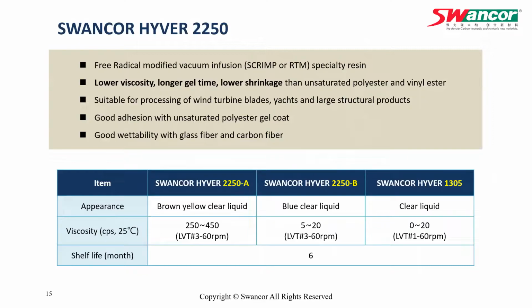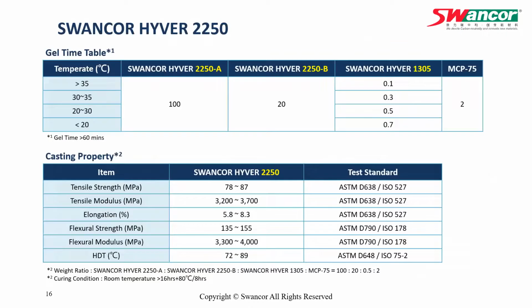And this table shows the appearance and the viscosity for 3 or 4 components. And the first one is the gel time table. We designed the operating condition from 20 to 35 degrees C, which suits most cases globally. Meanwhile, it's flexible with the specific components, with SWANCOR HYVER 1305 as catalyst at 0.1, 0.3, 0.5, and 0.7 respectively. And that all can meet a pot life longer than 60 minutes.